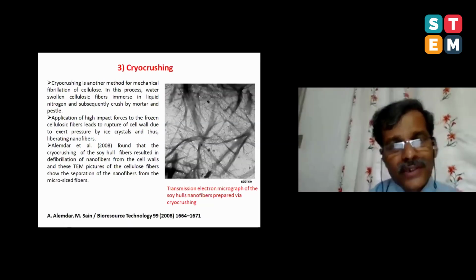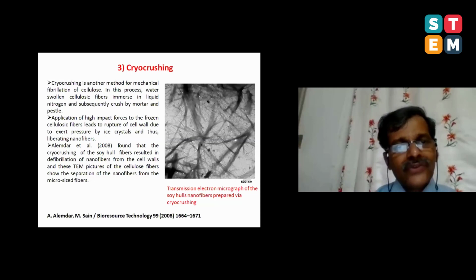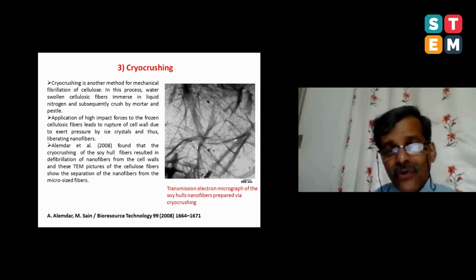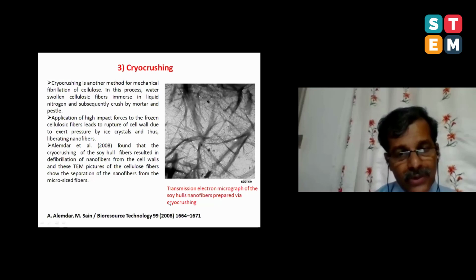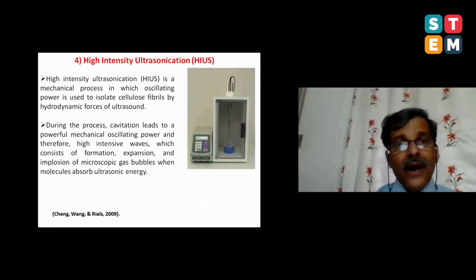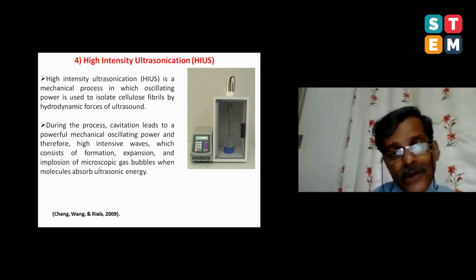Next is cryo crushing. You decrease the temperature, going to sub-zero temperature by cooling in liquid nitrogen, and then you apply high impact forces. As a result of this, you can transform the microfibers into nanofibers. You can see the transmission electron microscopy of soy hulls nanofibers made by the cryo crushing process, thanks to Sain and group. The next method is the high intensity ultrasonication process, also called HIUS. It's a mechanical process in which oscillating power is used to isolate cellulose fibers, basically by hydrodynamic forces of ultrasound.